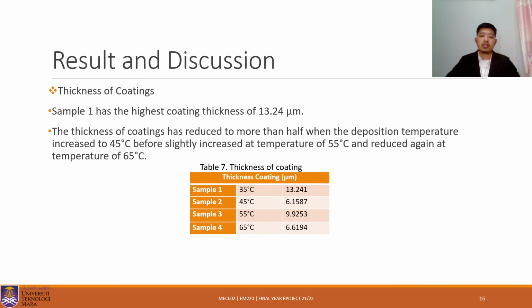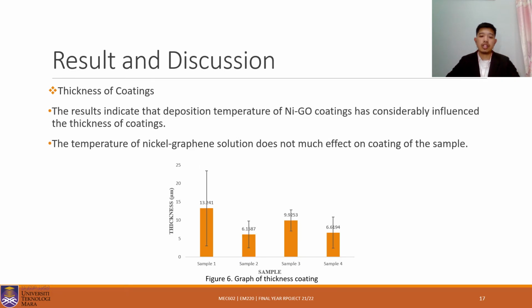For the thickness of coating, sample 1 has the highest coating thickness of 13.24 micrometer. The thickness of coating reduced to less than half when the deposition temperature increased to 45 degrees Celsius, before slightly increasing at a temperature of 55 degrees Celsius and reducing again at a temperature of 65 degrees Celsius. Table 7 shows the thickness of coating for every sample. Data from table 7 were plotted in figure 6. The result indicates that the deposition temperature of nickel graphene oxide coating has considerably influenced the thickness of coating. The temperature of nickel graphene solution does not have much effect on the coating of the sample.